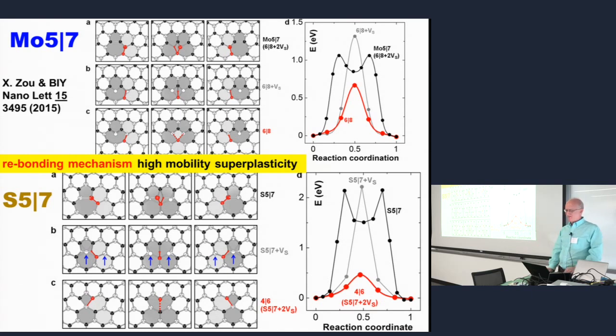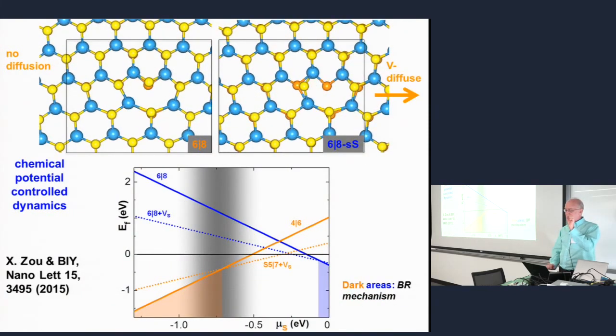And so basically, theory predicts here, and they observed in experiments just one dislocation moving, that by controlling chemistry, you can bring this brittle crystal into a plastic state, even almost at room temperature, at very low temperature, not like carbon. This shows you the mechanism, but I don't have time to dwell on the mechanism, how it happens, why the barrier is so low.